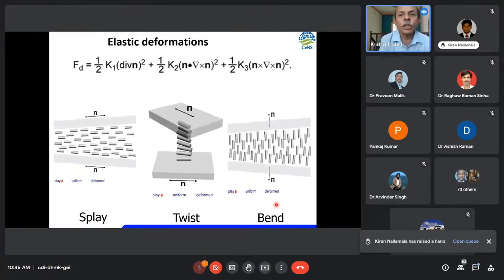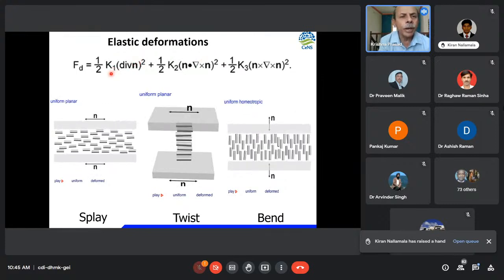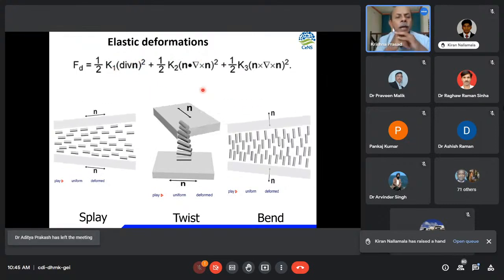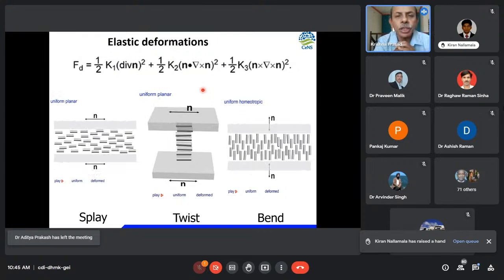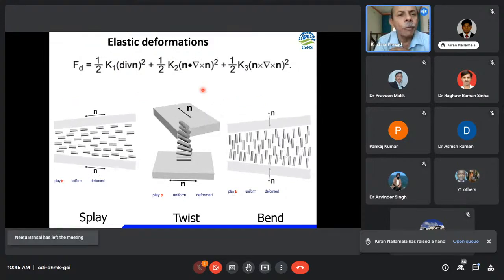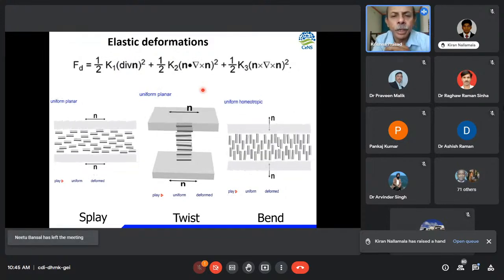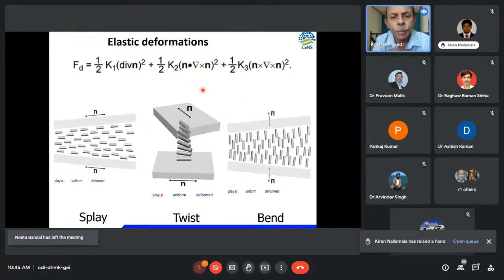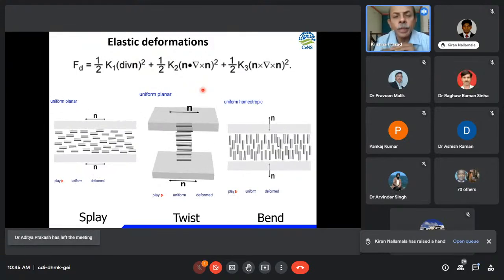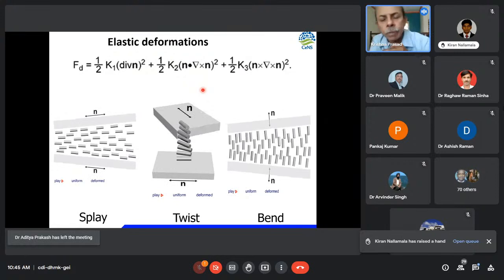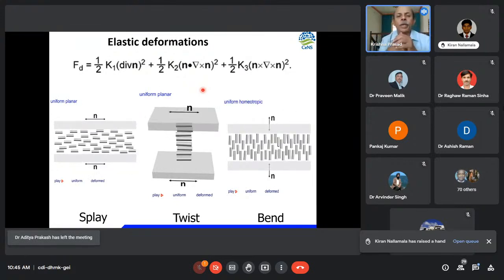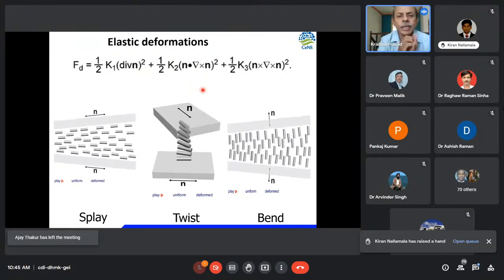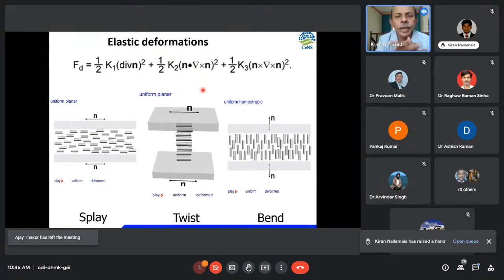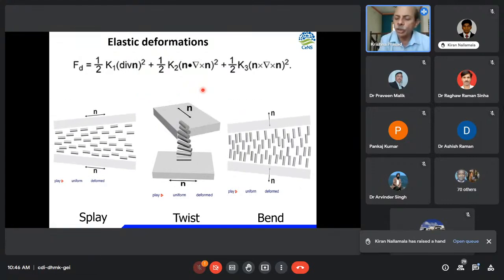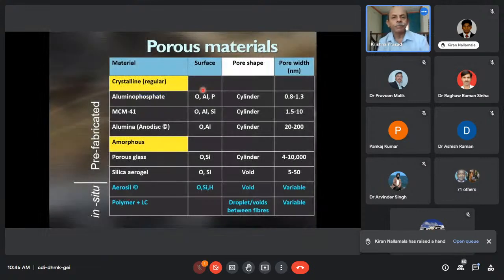So the free energy of the system will depend on each of these elastic constants which govern such deformations, and one can arrive at how simple it is to deform these kinds of molecules, the energies involved being extremely small, or in terms of the forces involved, these are in the piconewtons. So therefore, even a small perturbation such as a dust particle can deform these systems very easily.